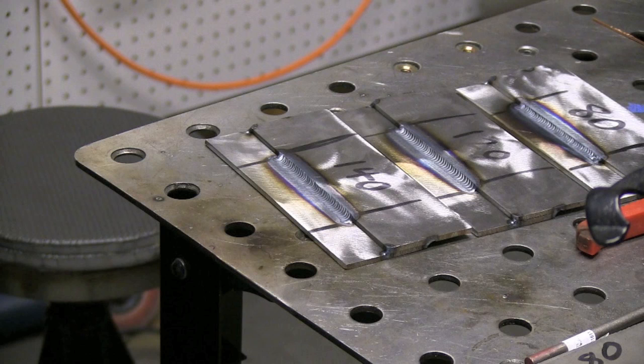Don't want to make anybody afraid of heat input or like it's a bad thing. It's just something to be concerned with because it can affect the properties of the weld and the metal. I'm welding cold rolled steel here on this bench, so it's going to affect it less than most things. It will have somewhat of a softening effect on it because the grains in that cold rolled metal will recrystallize in a certain area and soften up and be basically an annealed area and you'll lose the benefit of the cold working.